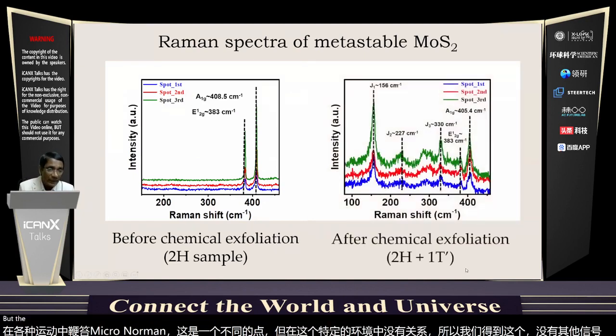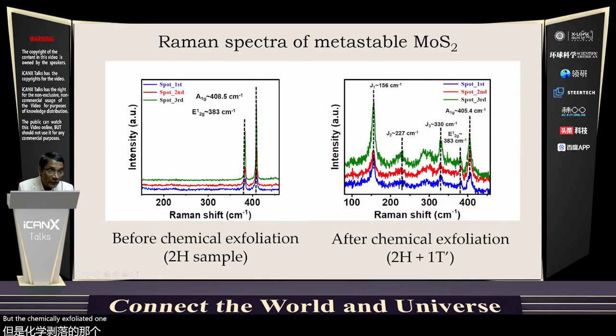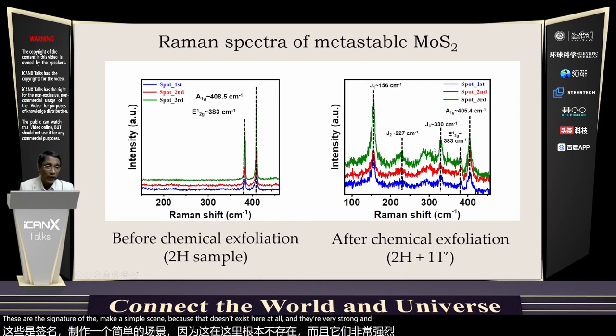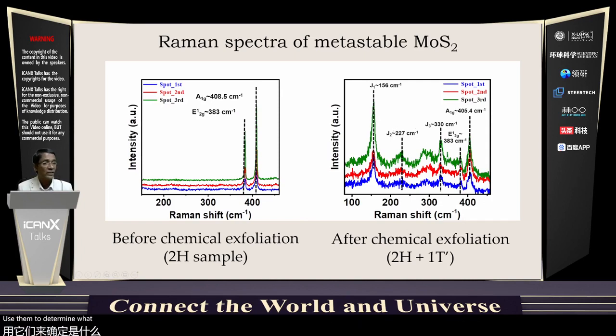But the chemically exfoliated one shows me this remnant of the H phase, these two, the A1g and E1_2g, but shows me many other strong lines, which often come as J1, J2, J3, etc. These are the signature of the metastable state, because that doesn't exist here at all. And they're very strong. And therefore, I should be able to use them to determine what the structure is, because the frequencies must be extremely sensitive to the structure.